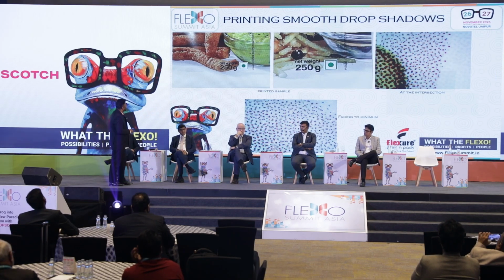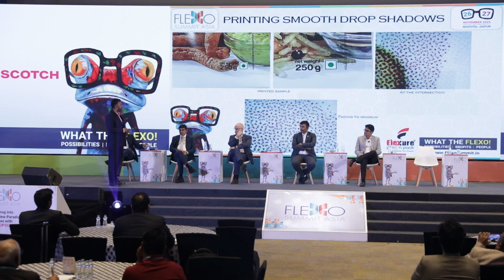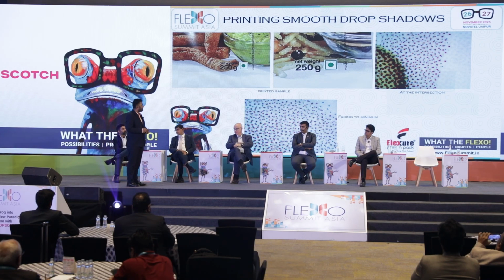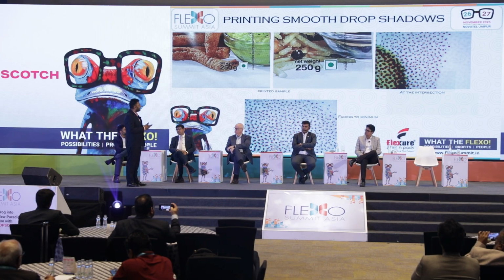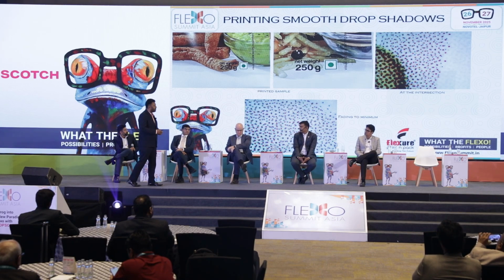Printing smooth drop shadows. One more way to resolve this is to print the drop shadows with CMY in such a way that the tonal value of black is achieved. You can also eliminate black but reach that level by, let's say, increasing the tonal value.